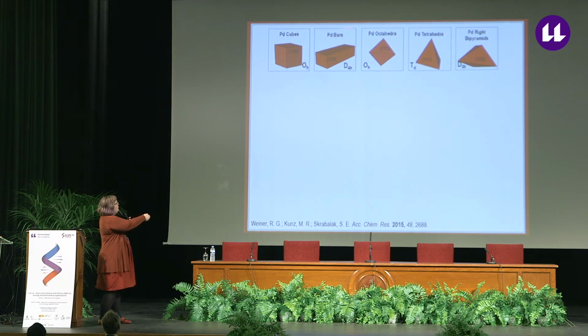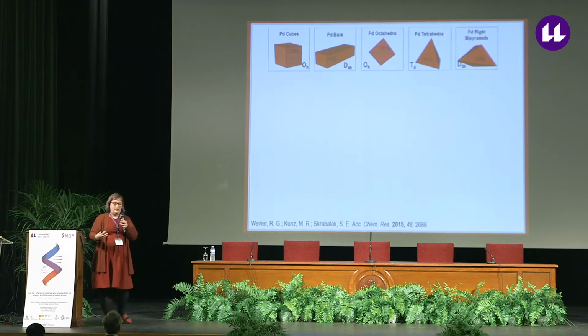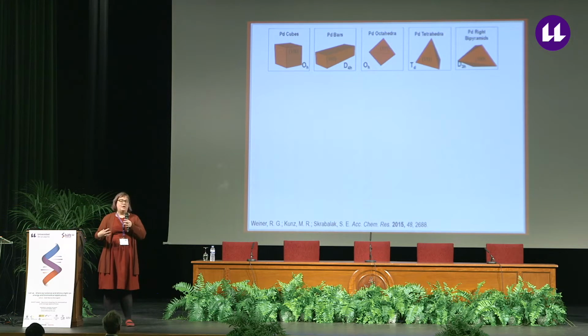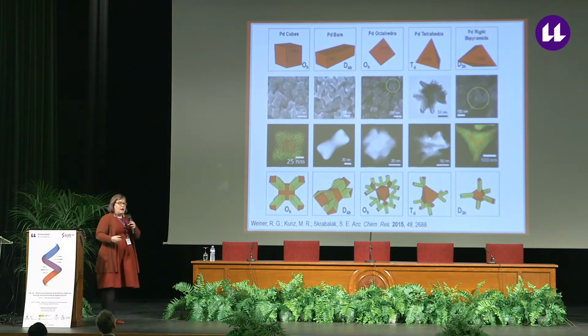So for example, we could select other shape-controlled seeds that we can make based off of reports in the literature. For example, palladium cubes, palladium bars, palladium octahedra, tetrahedra, or right bipyramids. They have different starting symmetries, but if we select our deposition kinetics such that, for example, branched nanocrystals are favored, we'll get branched nanocrystals with different symmetries. And so shown here are some of these examples. For example, with the palladium bars, we end up with these 8-branch sort of bow tie-like structures where there's one branch emerging per vertex.